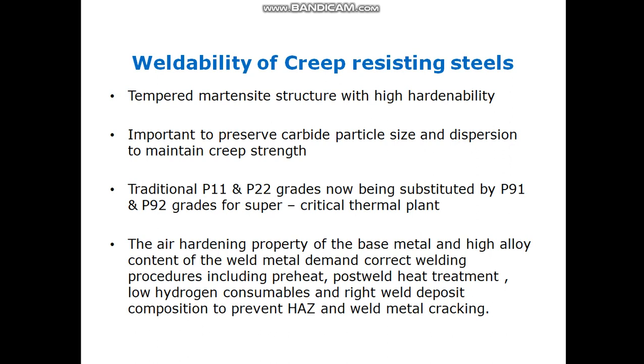For Cr-Mo steels, in order to take the full benefit of the strength and properties of the material, the Cr-Mo steels have to be post-weld heat treated because the as-weld martensitic structure is very high and the martensitic structure has to be tempered, and the carbide particle size and their dispersion is to be managed to maintain the creep strength. There are traditional P11 and P22 grades. They are now being substituted by P91 and P92 grades for supercritical thermal plants.